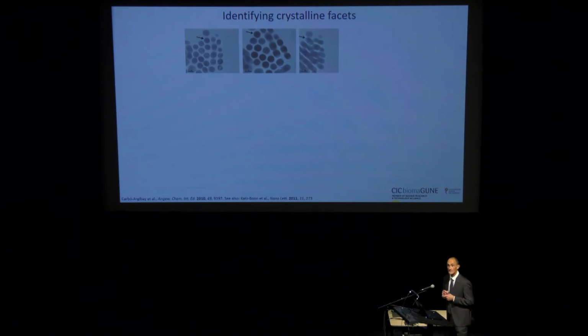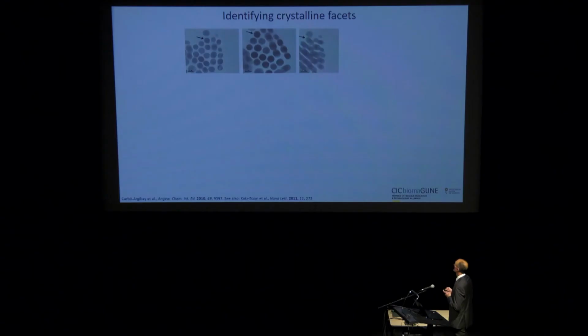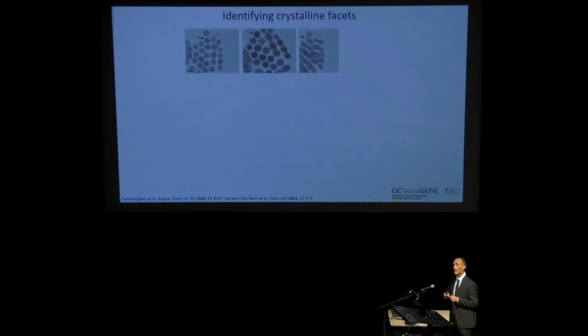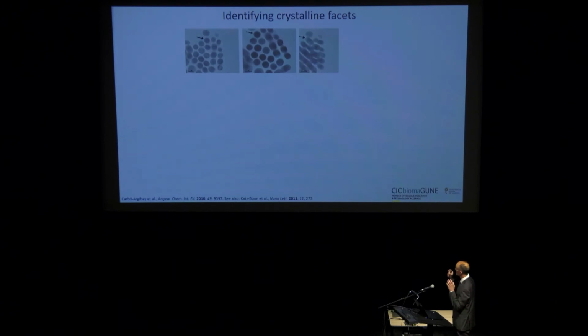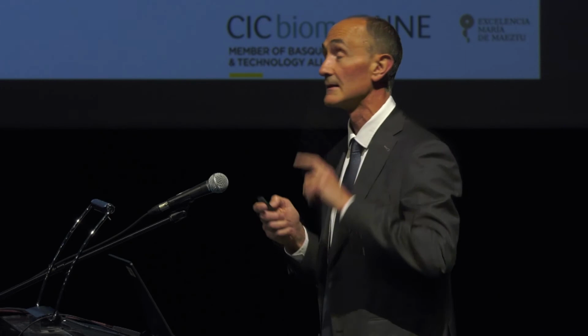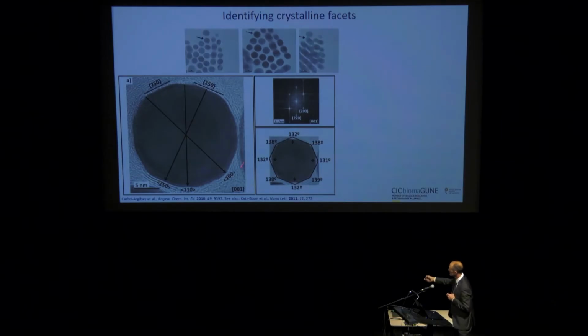Now, coming back to the nanorods, another example of characterization. For a long time, it has been claimed that for single crystal nanorods, the lateral facets are a combination of 110 and 100 facets of the FCC crystal. Now, my student Enrique Carbó Argibay was working with assemblies of gold nanorods which were standing perpendicular to the TEM grid. What here looks like spheres are actually the cross-sections of standing nanorods. By tilting the grid, you can see that they become deformed, because now you're watching a tilted nanorod. If you find the right orientation between the electron beam and the standing nanorod, you may be able to do high resolution of the cross-section.